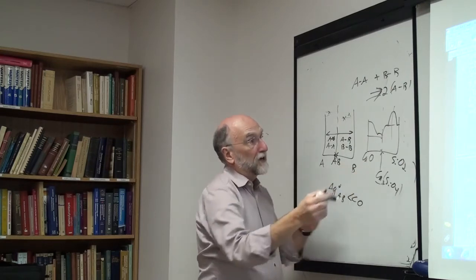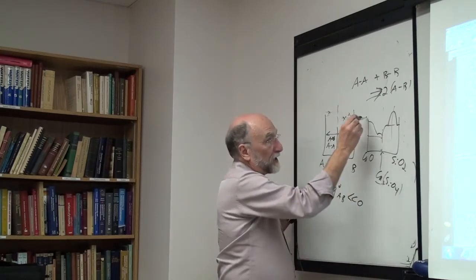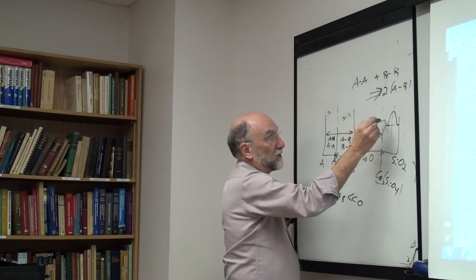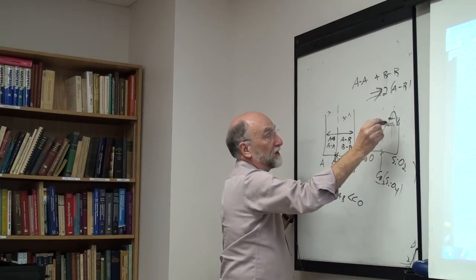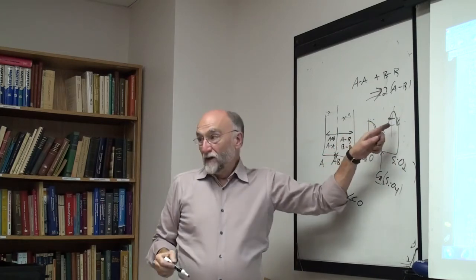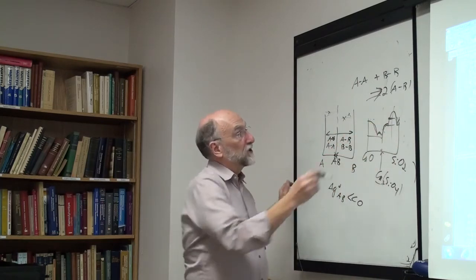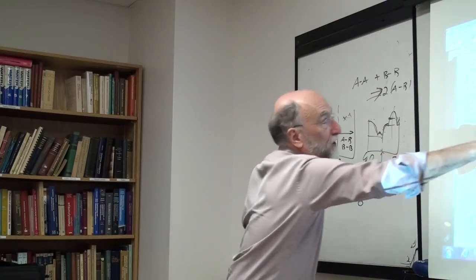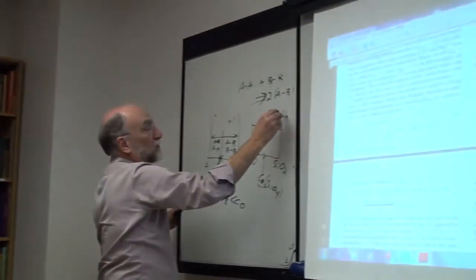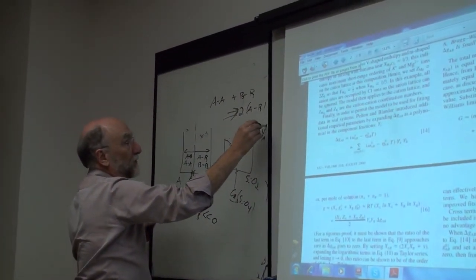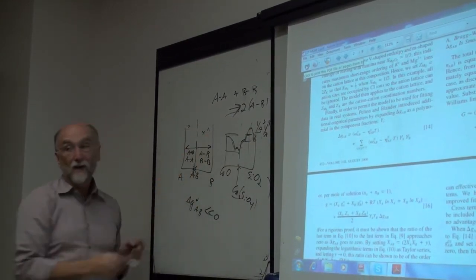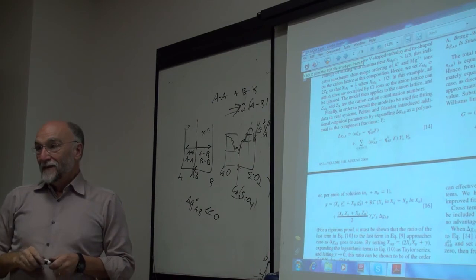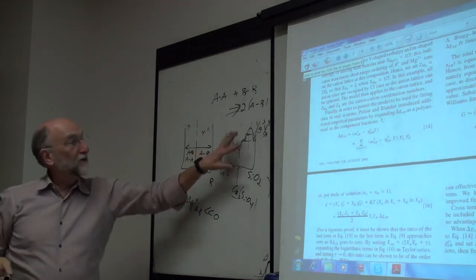Generally, with only a couple of terms, you can get a pretty nice fit to everything on this side, but over on this side you have a lot of trouble fitting this miscibility gap, and this is the hard side to fit in your optimization. So you start to introduce higher order terms, polynomial terms in Y to the fifth, Y to the fourth, and whatever to try to fit this. And every time you add a term here, you totally mess up what's happened on this side, because you have to fit the whole thing together.